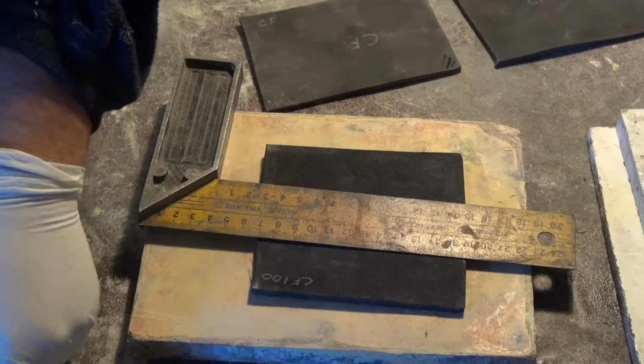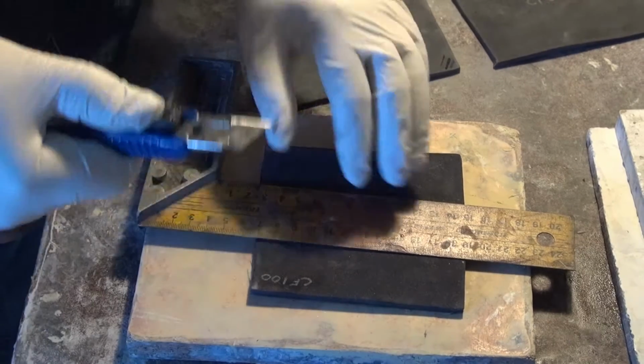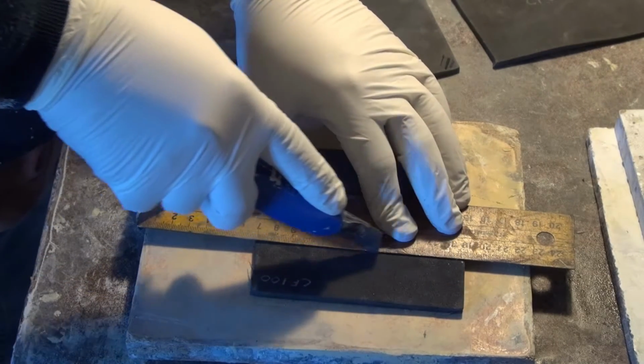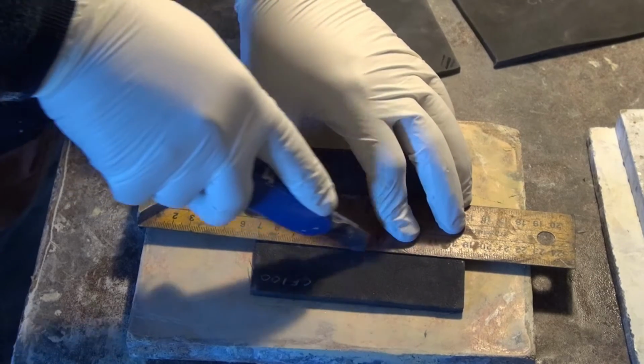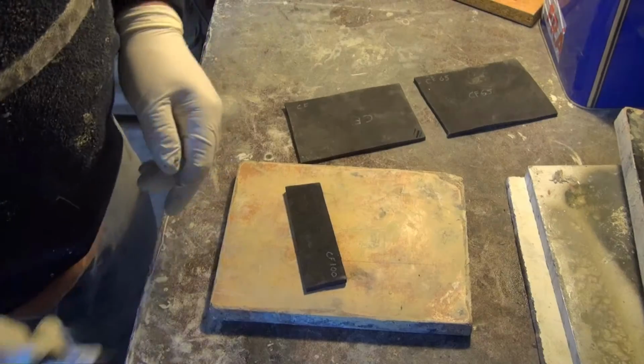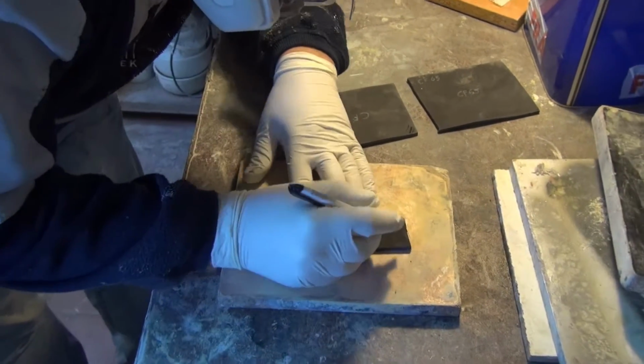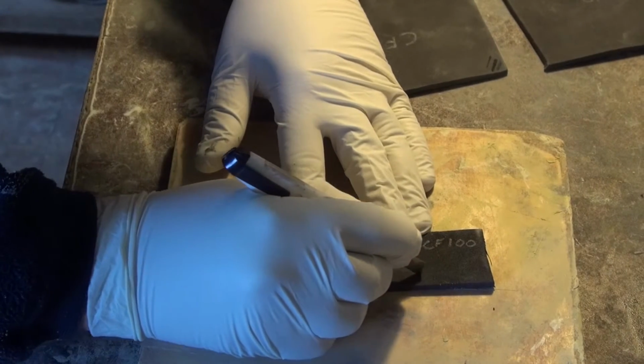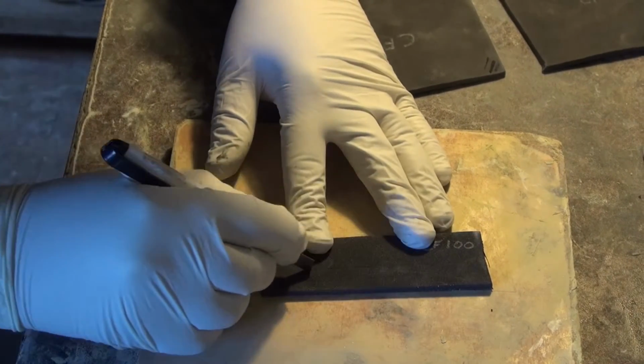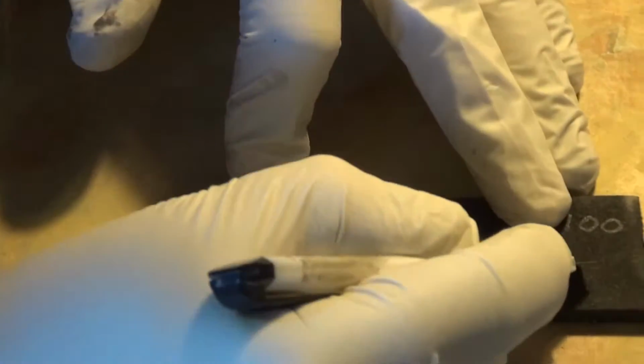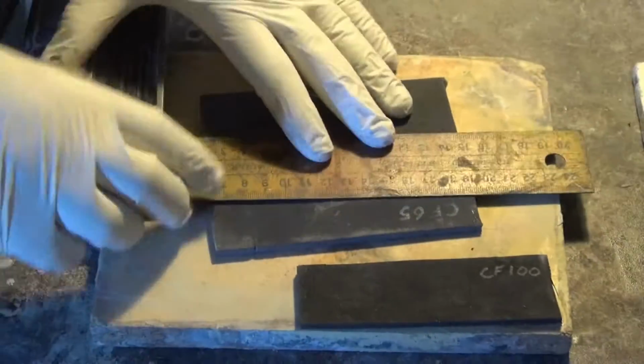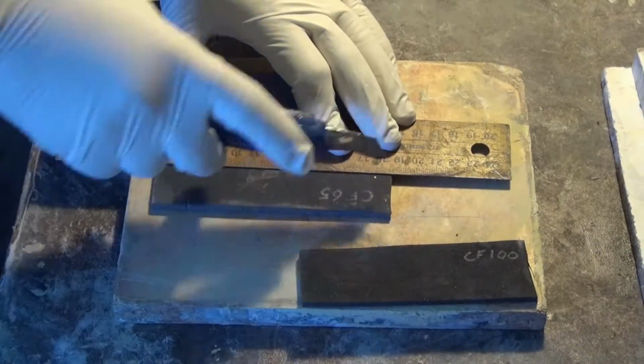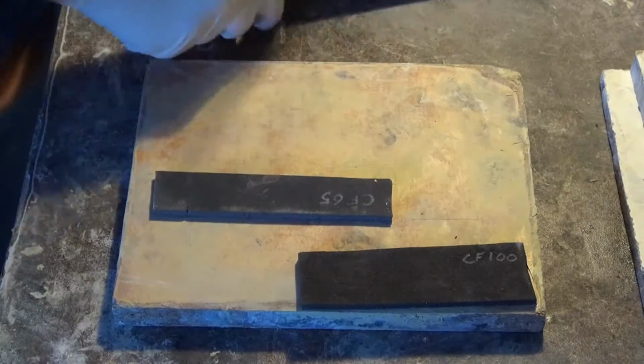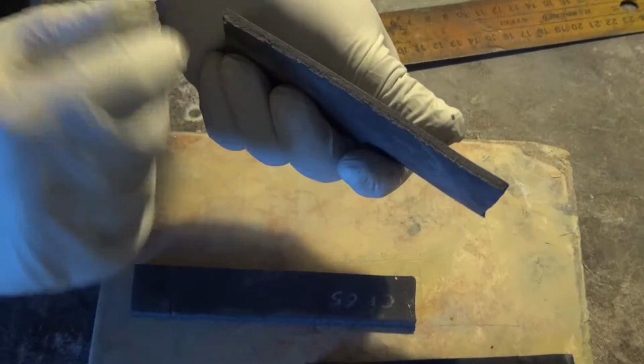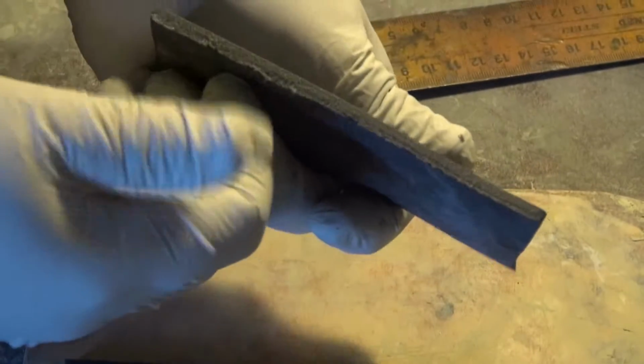Next, we made some tests for cutting, gluing, and molding with heat. First, the cutting. The first sample to be tested was the CF100. It was cut all the way through in all its length. Then, some half cuts were made, which are superficial cuts to give some detail to the pieces. The procedure was repeated on the craftfoam and CF65 samples. While cutting, we can see that the blade leaves some dragging marks on the foams, but this can be due to the fact that the blade is not sharp enough.